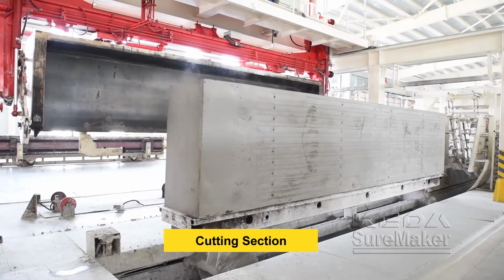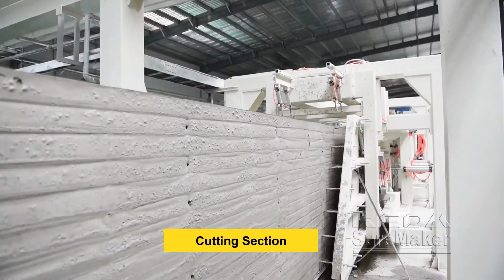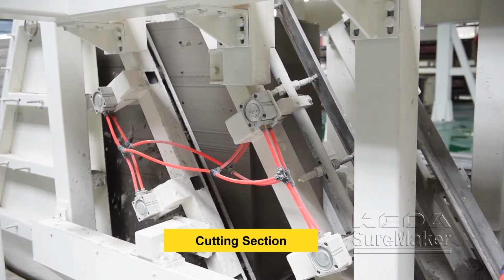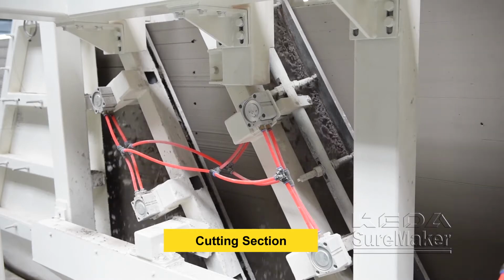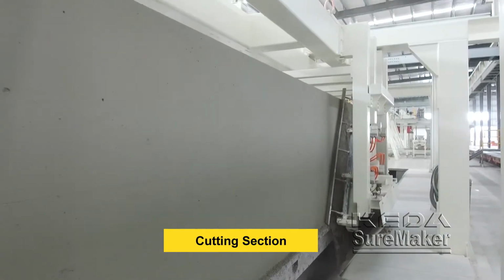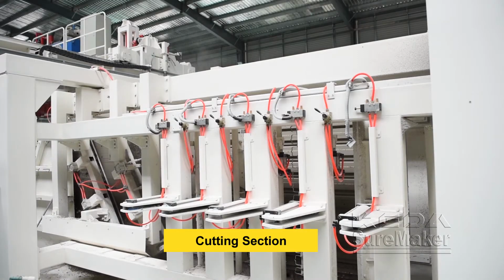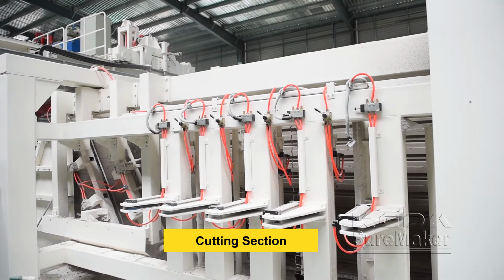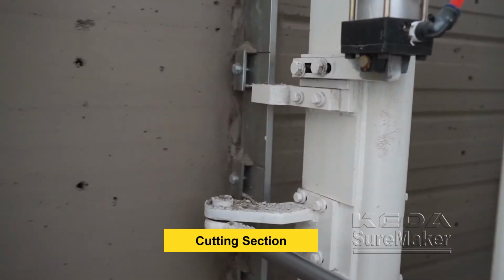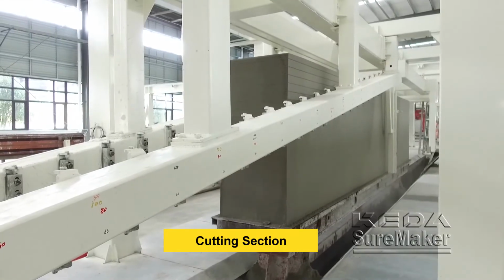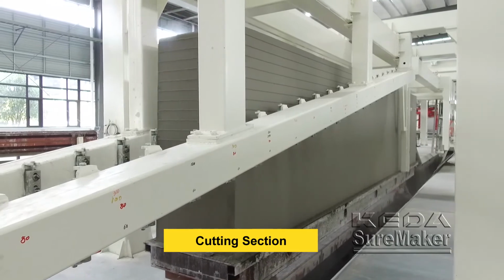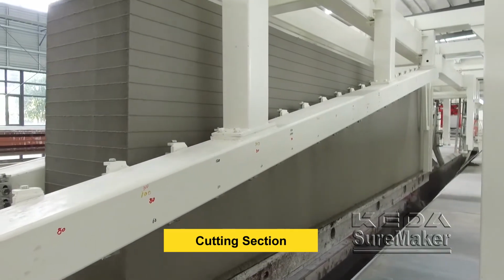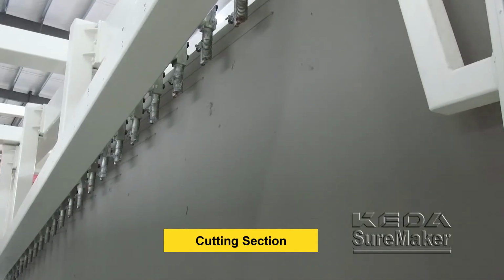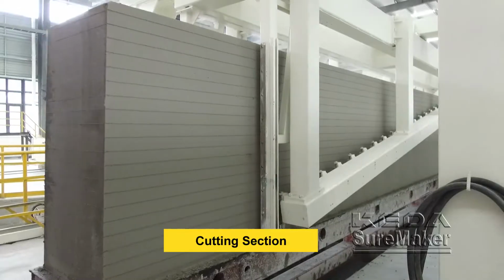The surface cutting device of the cutting machine adopts the combination of 3 steel wires and 2 scrapers to cut the both sides surface of green cake smoothly. The cutter of grooving machine can be changed according to the production requirement, or make the concave and convex grooves on both sides of the panel. The cable stay beam horizontal cutting machine can cut thin panel with thickness of 50 millimeters smoothly without any settlement cracks.